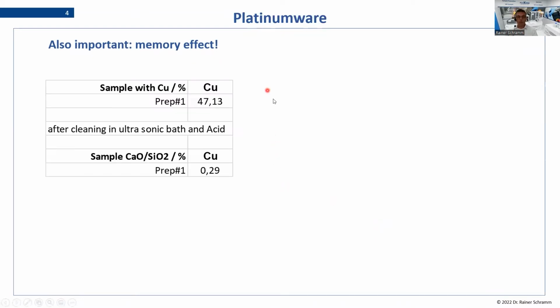Another point we have to take into account when we do such samples like sulfides with high element concentrations is the so-called memory effect. That means, for example, for copper ores with a very high copper content, let us assume we have a sample with 47% copper, and then I pour it out into my mold and I prepare the next sample, and let us assume the next sample is free of copper, then still I would measure something around 0.3%. Why? Because the copper is going into the platinum, and in the next fusion it's bleeding out, and this contaminates our next sample. So there you have to be careful. That means you need to do a kind of a cleaning fusion just with flux, or with another sample which is free of copper, so that the copper is then reduced in the platinum, or you have your own set of Platinumware only for this kind of application.